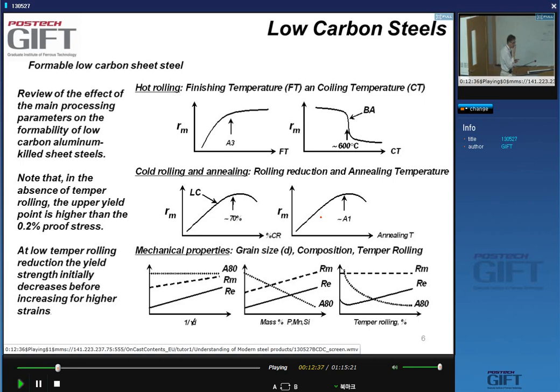Your properties will depend on almost all the processing parameters, but there are a number of key parameters. For instance, for the low carbon sheet steel, in hot rolling, we find that the higher the hot rolling temperature is, the more my R value increases. However, there is a very strong dependence on the coiling temperature. If we have low coiling temperatures, we can achieve high R values. If we have a high coiling temperature, the same steel will give me a much lower formability. And the reason is, as you already know, and we'll go through it quickly today again, because of the precipitation of aluminum nitride during batch annealing.